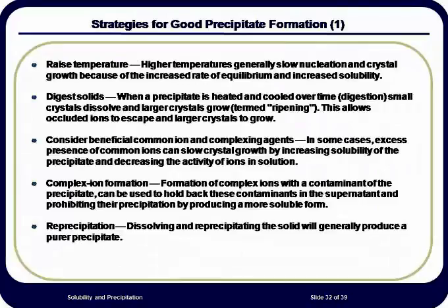Addition of complexing agents or common ions to increase solubility will aid in a better crystal formation. An example of this might be to load a solution of ferric ions with chloride before precipitating the hydroxide. The chloride will complex with the iron, causing a slower precipitation of the hydroxide.